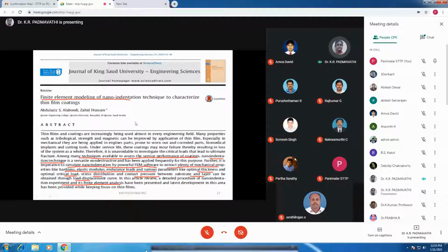Actually, many techniques are available to assess the performance of the coatings. And the nano indentation technique is a versatile, non-destructive testing. At a very minute nanometer level, only an impression is formed over the surface, so it won't affect the material's properties. It is imperative to simulate nano indentation with powerful FEM software to extract plenty of mechanical properties like hardness, elastic modulus, endurance loads, and various parameters like optimal thickness, optimal critical load, stress distribution, and the contact pressure between the substrate, that is the workpiece over which the layer of coating is applied, which can be measured with the help of the load displacement curve.